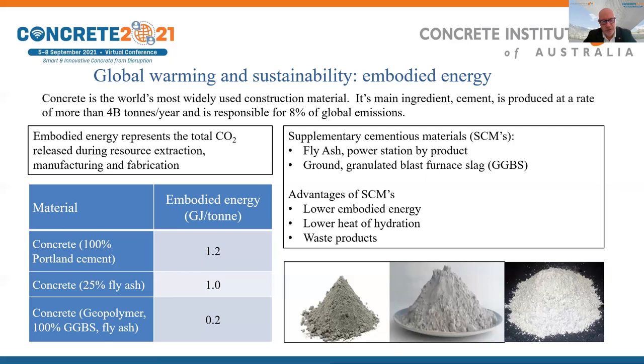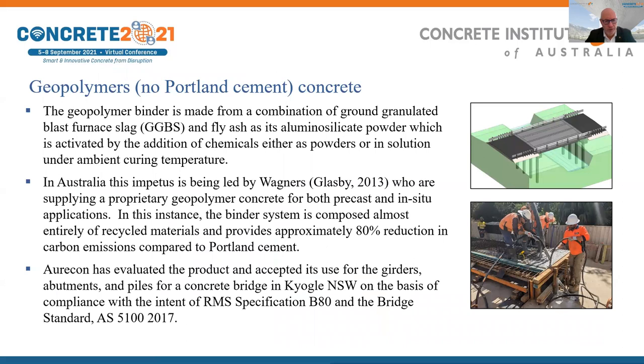To take it one step further, though, is to essentially look at eliminating Portland cement by the use of geopolymers. And you can see the embodied energy per ton for geopolymers is substantially less than that for cement. In Australia, Wagner's leading the charge here with their proprietary geopolymer product that they're using for both precast and cast in situ applications. And we've designed a bridge that has been built using geopolymer concrete for piles, abutments, superstructure at Kyogle in northern New South Wales, and appears to be doing really well.